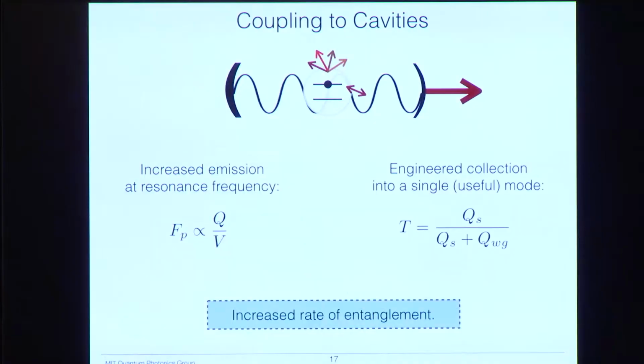So now, one thing that we can do to improve that is couple the NV center to a cavity. A cavity is an optical cavity, and it will give you two things. The first is increased emission at the resonance frequency of the cavity. This is the Purcell effect. It's proportional to the quality factor of the cavity, or how long the light stays in the cavity, over the mode volume of the cavity. The second thing is that we can engineer the loss of this cavity into a useful mode. So we can create a very, very high Q cavity, but then introduce a loss mechanism into, for instance, a waveguide mode or a fiber mode. And then these two things together will give us an increased rate of entanglement.